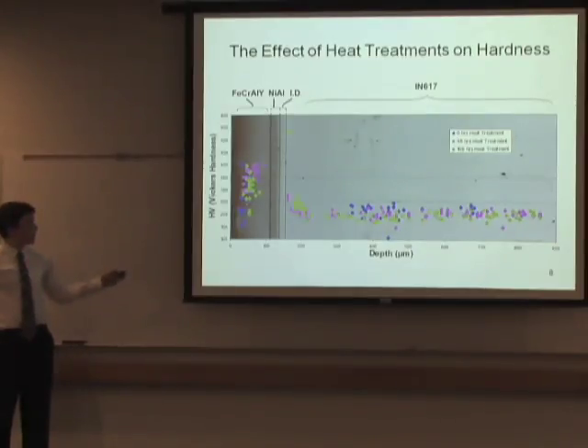And as you can see, some of our heat-treated samples in pink and green are given larger hardness ratings than that of the blue indents, which have no heat treatment. And we think this is because of the precipitates that occur due to interdiffusion after heat treatment. We think that they're actually making the material stronger.